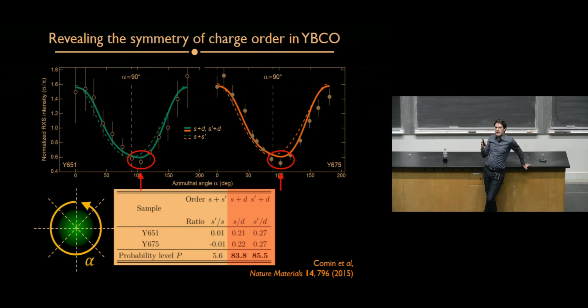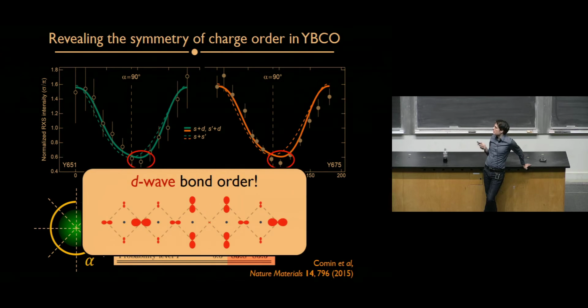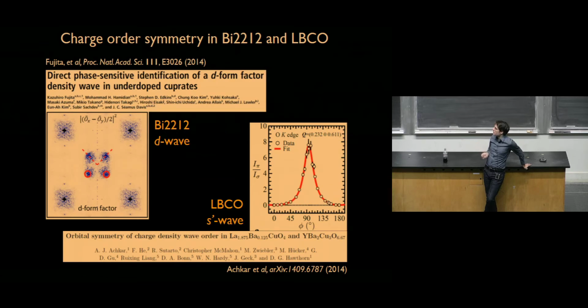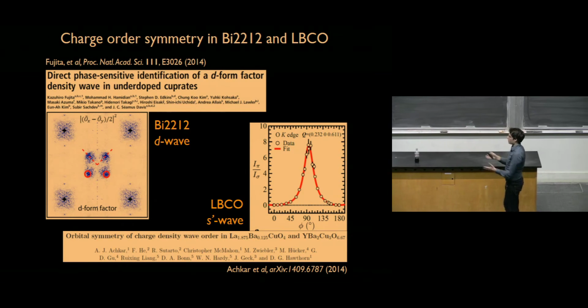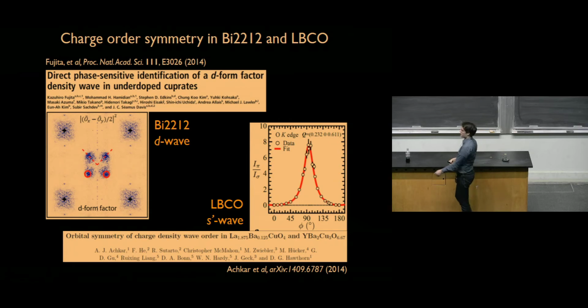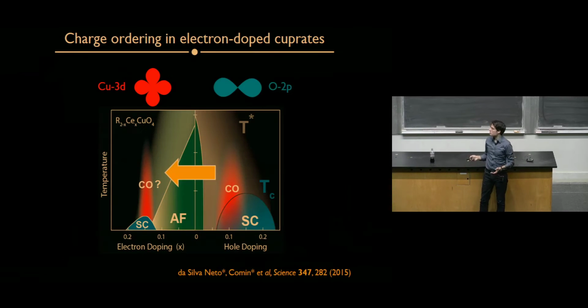So it breaks some kind of local fourfold symmetry, and the conclusion is that we have this type of D-wave bond order, which clearly breaks this symmetry locally. So it clearly breaks this fourfold symmetry. And you can see it quite clearly in this diagram here. So this was then later discovered in other compounds. So this started a whole new kind of direction of study on the local symmetry of charge order.